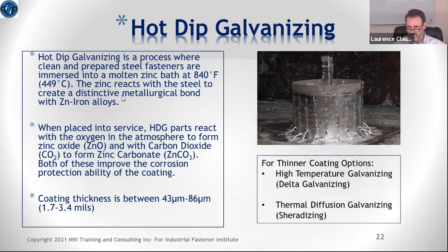By the way, I've skipped past the middle bullet point there, but one of the other advantages of hot dip galvanizing is that once the part is actually put into service, so once that part is actually exposed to the atmosphere out there, it reacts with the oxygen and carbon dioxide in the air to form zinc oxides and zinc carbonates, and those actually boost the corrosion protection.